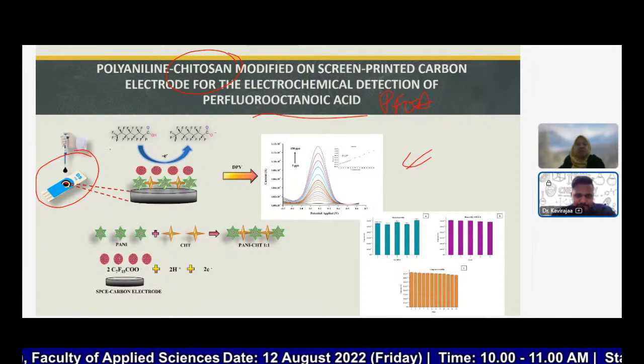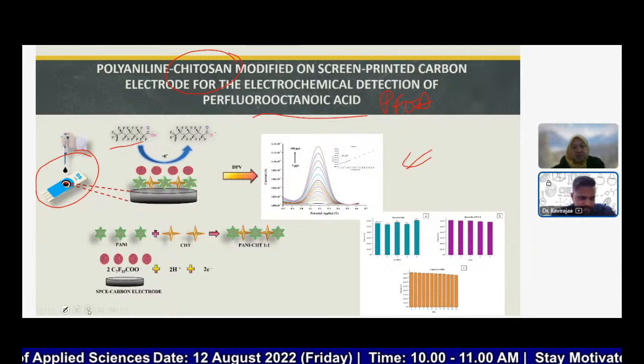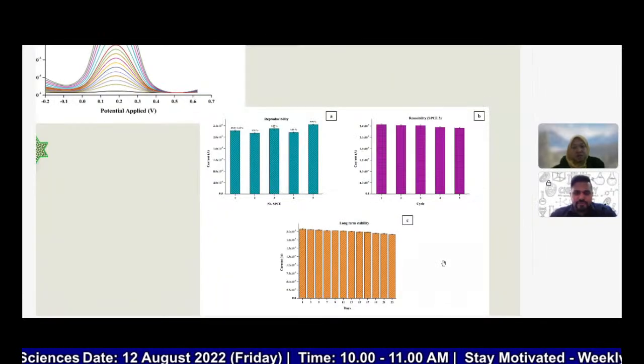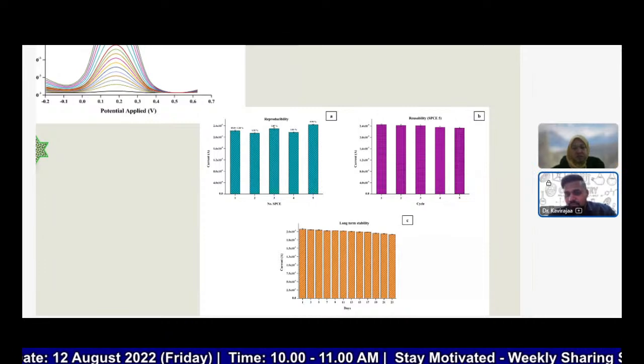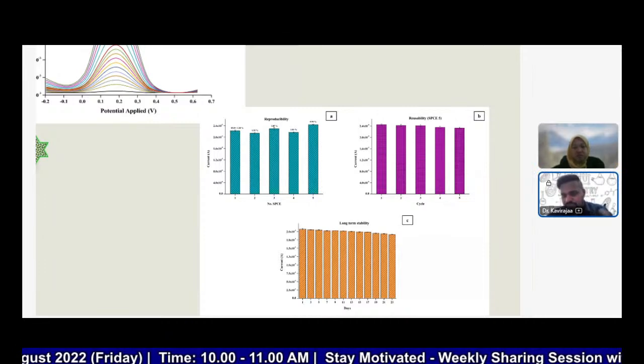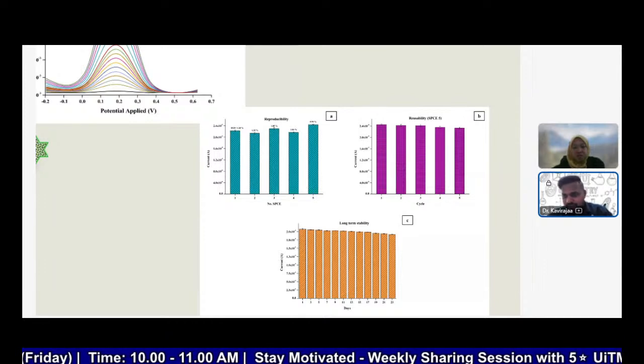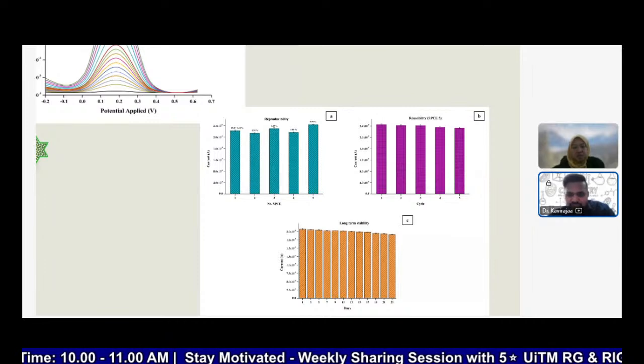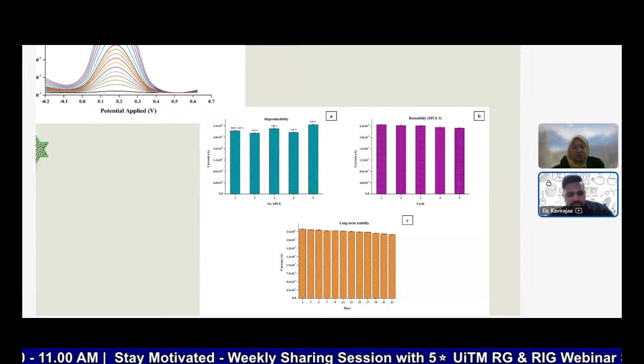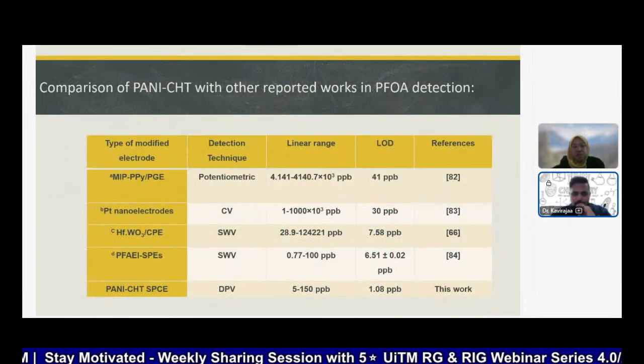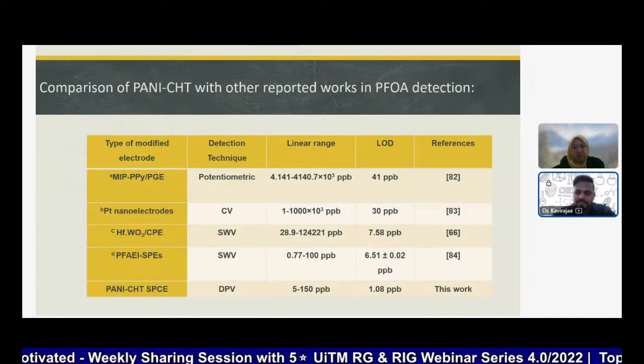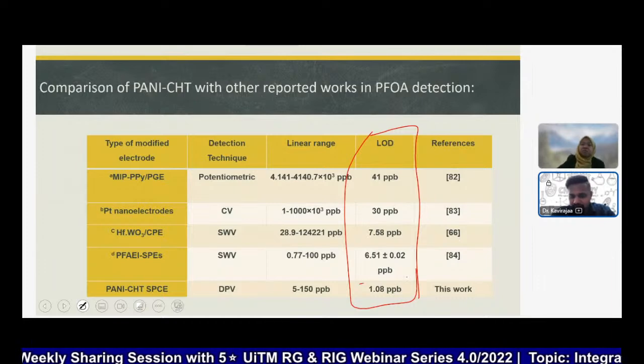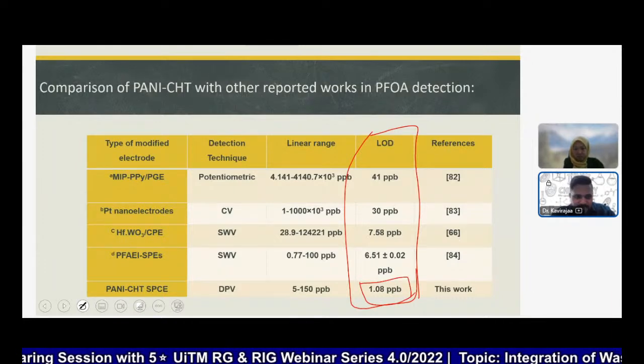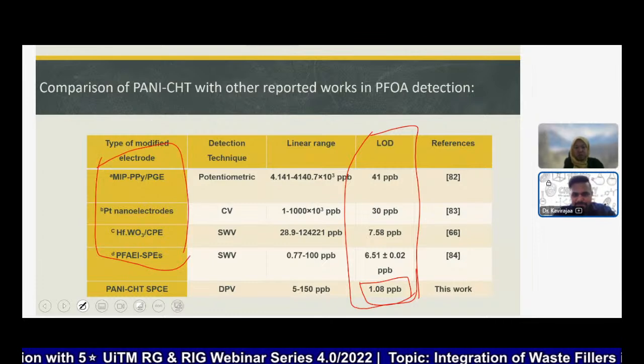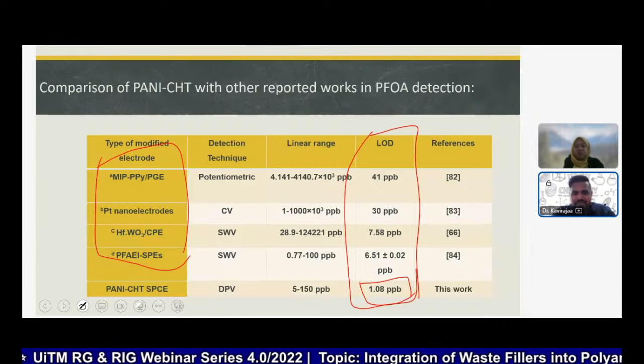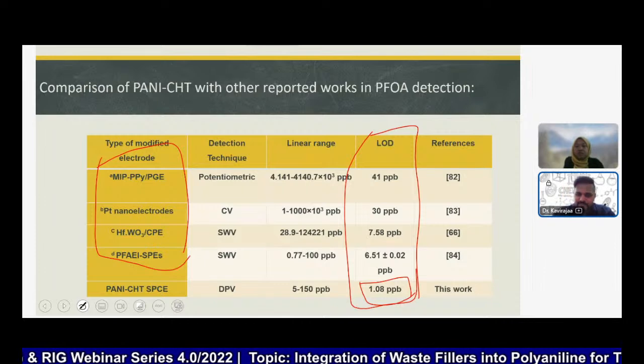As we can see here, it shows good reproducibility and also reusability, because one of the concerns is that screen printed electrodes are normally use and throw, but here we didn't throw, we can reuse it. Maybe we can go more than 5 times as well, but here we just used it 5 times. Even long-term stability, we can use it for about 3 weeks. And we compared it with some existing sensors in terms of limit of detection, and we were good. The limit of detection of the sensor that we developed is 1.08 ppb, because when we look at the other materials and study their papers, they seem to be more expensive compared to what we have developed here. Yeah, so that's the thing.